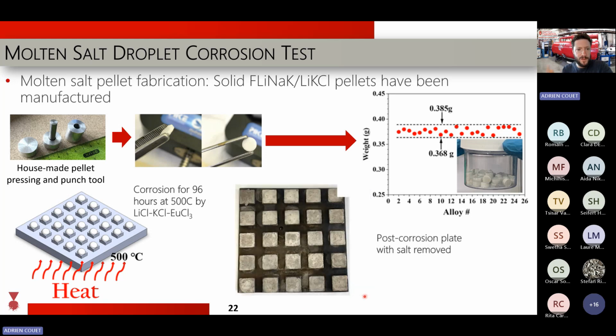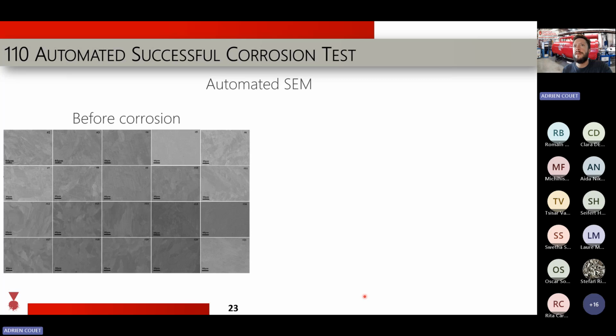You can remove the salt, store it for analysis, and then you can clean up the surface and look at it after corrosion for each one of your alloys. And this is before corrosion. So you see some polishing marks, right? Because we polish everything together, the polishing is not the best. But again, it's a high-throughput technique, so you're not going to get the super nice colloidal silica finish that you would get if you were to polish one or two samples together. But here you do 25 samples together, right?